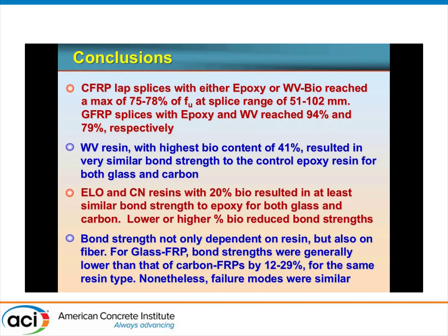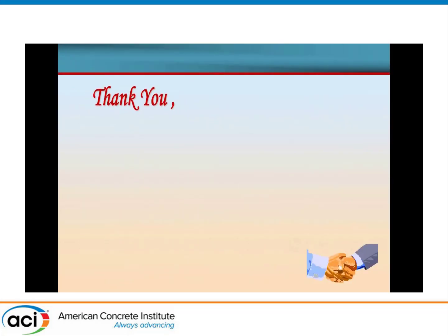The other thing is, and we probably know that already, so perhaps not a new conclusion, bond strength is not just dependent on the resin, but actually on the fiber for the same resin. So for glass FRP, the bond strengths were generally lower than that of the carbon by 12 to 29% for the same resin type. Nonetheless, the failure modes were essentially the same. So I think that's it, and happy to take questions.